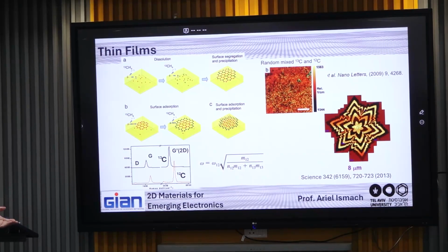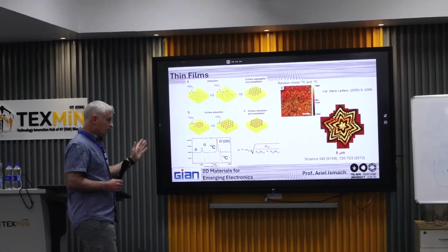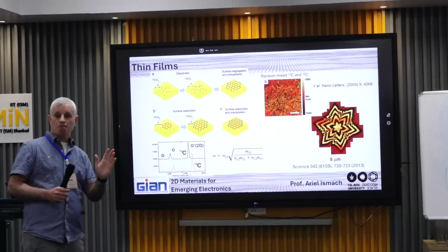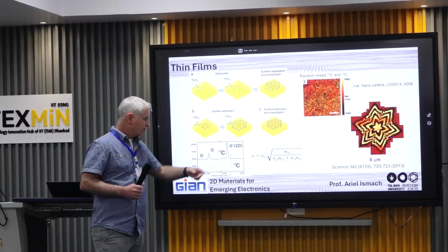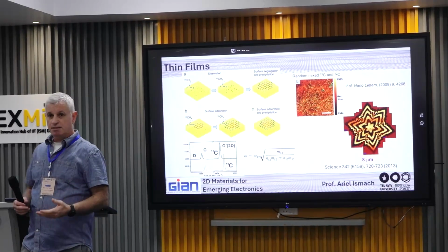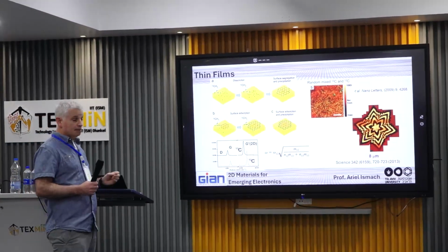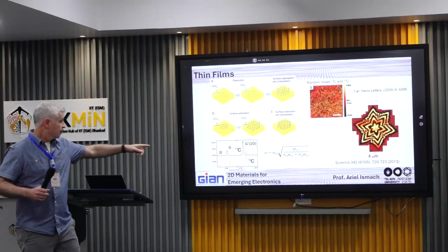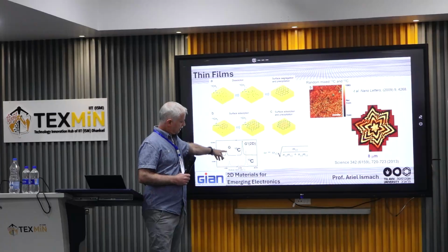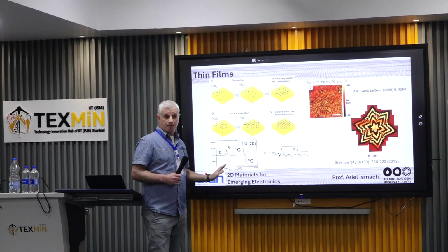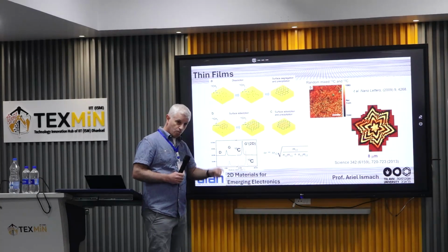In Raman spectroscopy, the same characteristic peaks of graphene, which we'll talk about tomorrow, will shift according to the isotopic composition, because the mass changes and therefore the vibration slightly changes, and you can detect that. So if you grow a graphene with C12 and a graphene with C13, you will get the same peaks but at different positions, because the vibration changes.